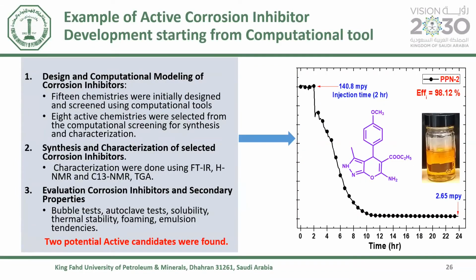So briefly, this is one of the projects where we used this tool, and we had a very excellent outcome from the project. First of all, we designed and used computational modeling to screen about 15 chemistries. We designed them from scratch. We built the chemistry from scratch, and then we computed a lot of properties. And then at the end of the day, we were able to have 8 of the chemistries that gave potential results. And then we synthesized them, about 8 of them. The result was very, very good because we got them in a very good yield.